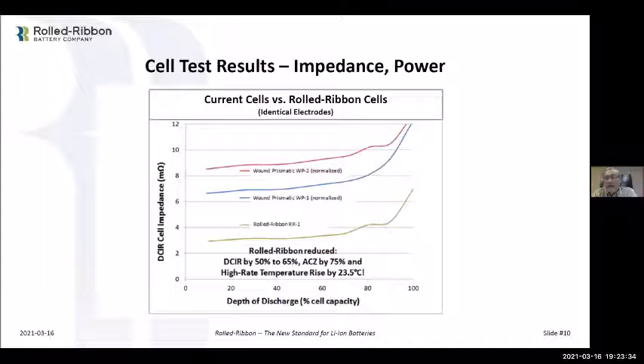At the end of the day, if you can keep it cool, you make it harder for it to hit that trigger point. And that's what we do. We keep the cell cool. But we don't sell Rolled-Ribbon on the basis that it's an order of magnitude safer, for example. If you really want an order of magnitude increase in safety, pick a different chemistry.